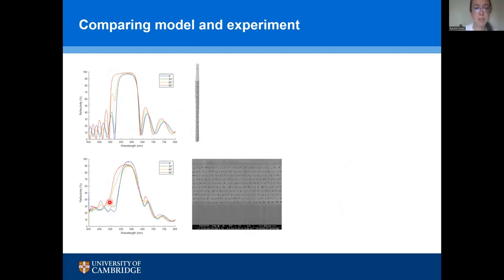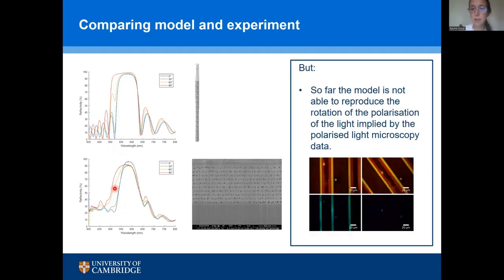And if we do exactly the same thing experimentally, the data is maybe not quite as clean as the beautiful model, but we see exactly that. We lose this part of the stop band as we go from the 90 degrees to the 0 degree polarization. So essentially what we have is a polarization dependent mirror, but only in this fairly narrow range in the short wavelength regime. The modeling isn't completely able to reproduce this rotation of the polarized light that we see in the polarized light microscopy though, but it gives us an idea that we really are starting to understand these structures.